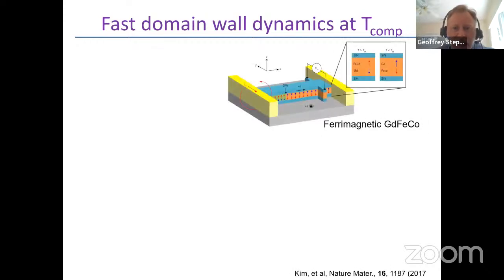And one way that one can explore this is with ferrimagnets. In rare earth transition metal alloys, which I'll come back to several times in this talk, these materials are quite interesting and useful, because by controlling either the composition of the rare earth with respect to the transition metal, or by controlling the temperature, because the two sublattices have different temperature dependencies, one can control the degree of compensation in these materials and actually explore the change in the nature of the dynamics between gyrotropic or not.